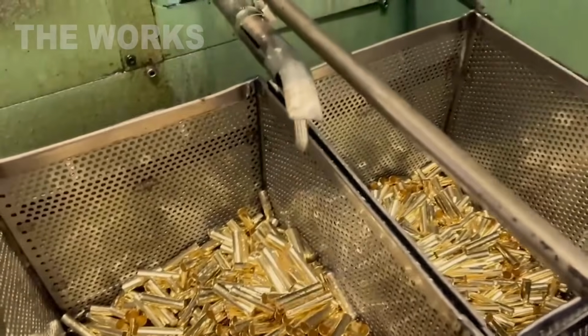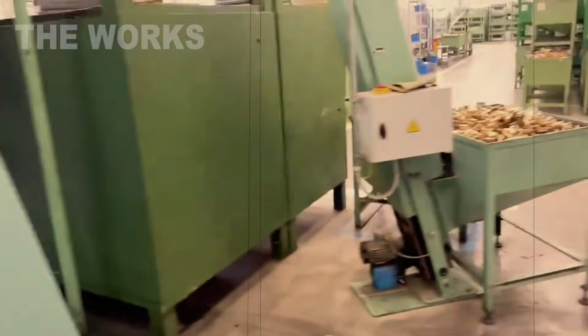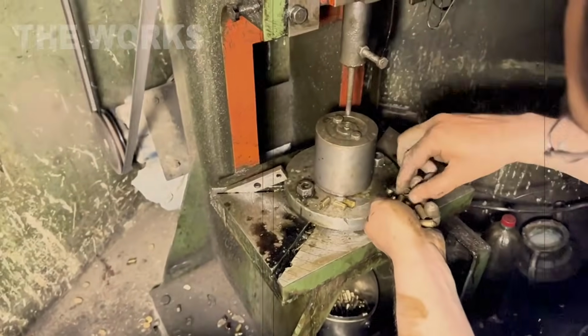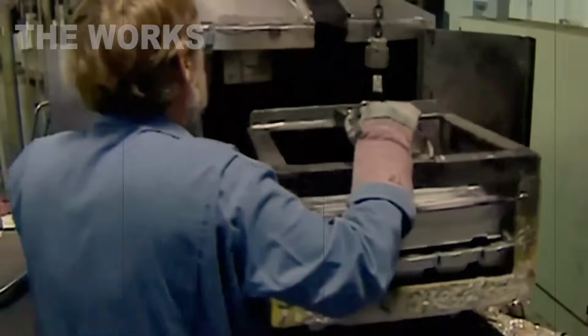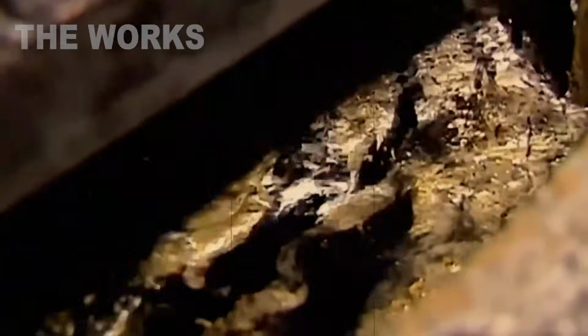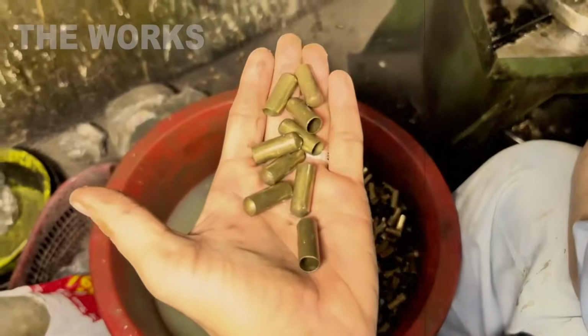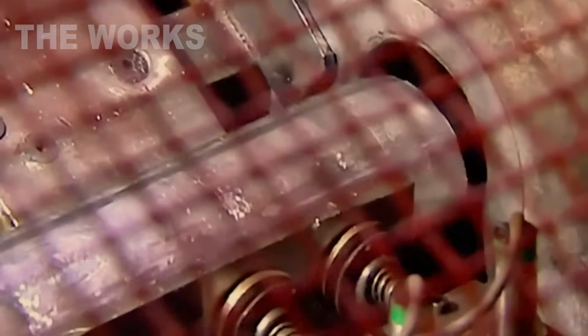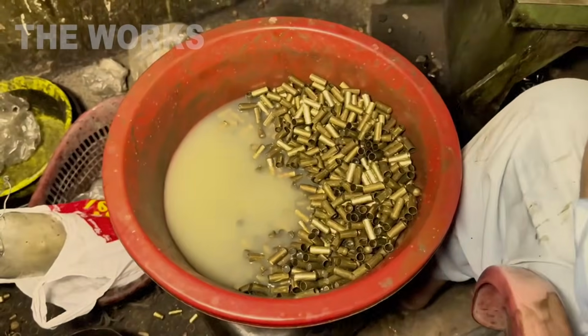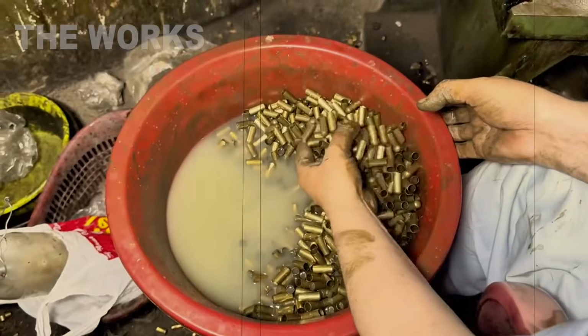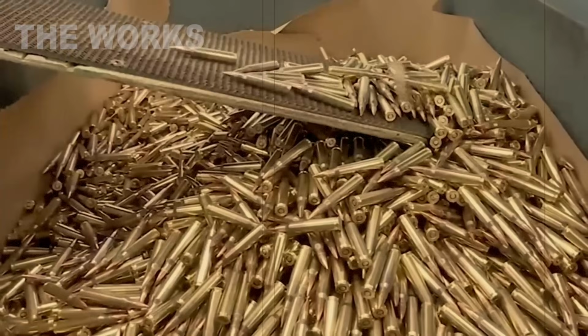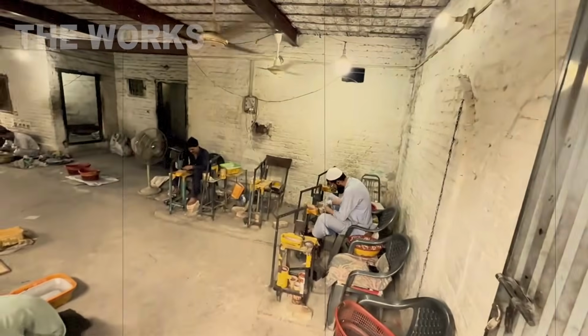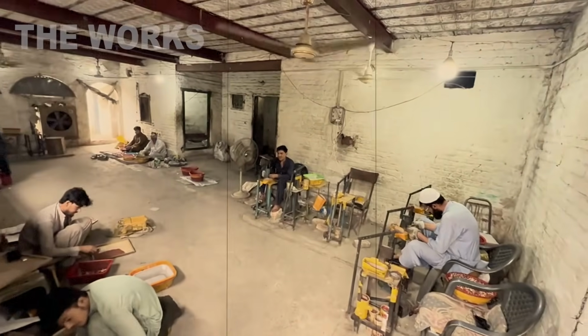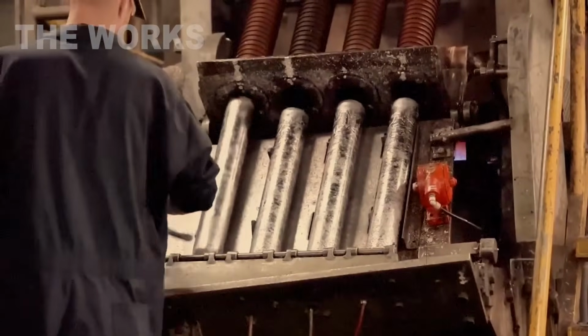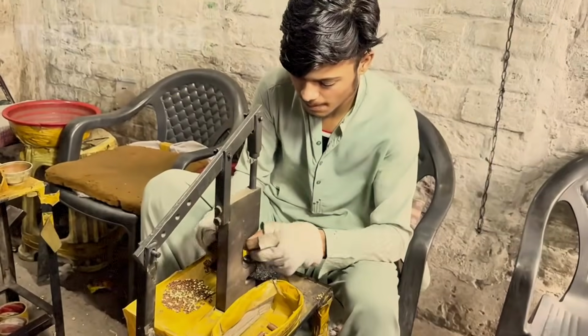Each case after drawing is annealed, heated to 540 degrees to relieve internal stress in the metal. Otherwise, the case could crack during firing. It's then cooled in water and cleaned in an acid solution. Next comes calibration and weighing. Cases pass through a high-precision laser control system. Weight discrepancy means automatic rejection. Length, wall thickness, and even acoustic response are checked. Special sensors detect whether there are microcracks in the case. Finally, the case is trimmed to precise length, a groove is cut for the primer, and the neck is expanded.